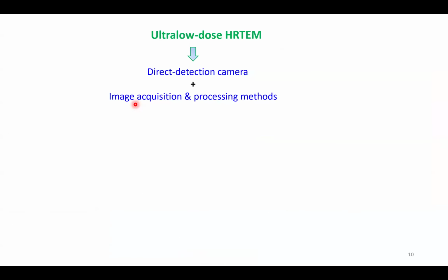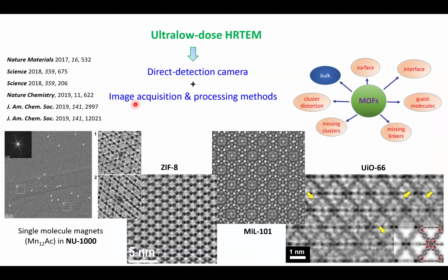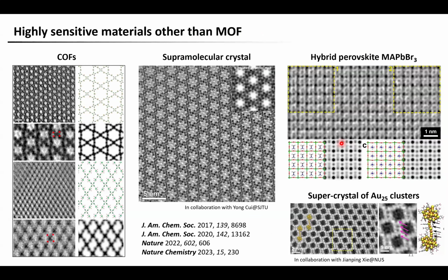And this technique works pretty well. It has allowed us to acquire high-resolution images for many MOF materials for the first time, which were conventionally considered not imageable using TEM. So our study focused on local structures of these MOF crystals, such as surface, interface, guest molecules, defects, and so on. Because these local structures are very challenging to investigate using other characterization tools. And this technique is not limited to imaging MOF materials. It can be generally applied to other beam-sensitive materials. For example, covalent organic frameworks, COFs, supramolecular crystals, porous glass, and so on. So like MOFs, these materials were traditionally considered not imageable using TEM.